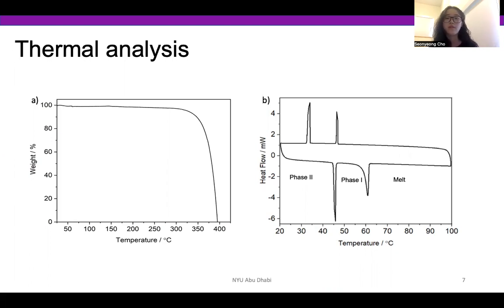And the result is shown in figure B. And the plastic phases are actually where the materials show local orientational and dynamic disorder that allows fast ion transport. And for practical usage, it is desirable for this plastic phase to occur around room temperature. And our sample showed this plastic phase after 45 degrees Celsius.